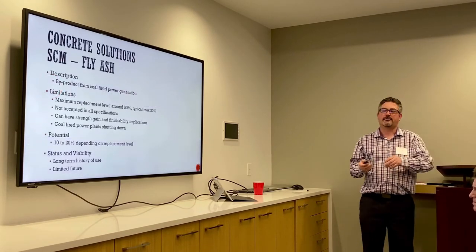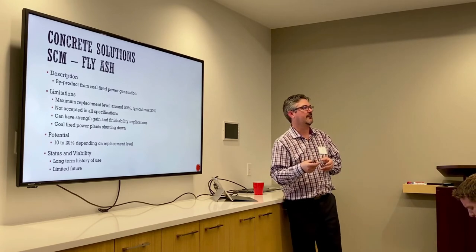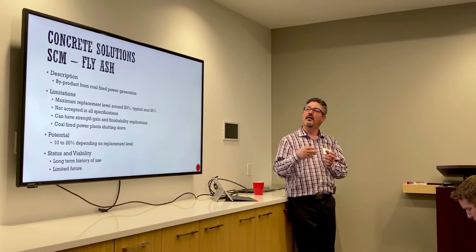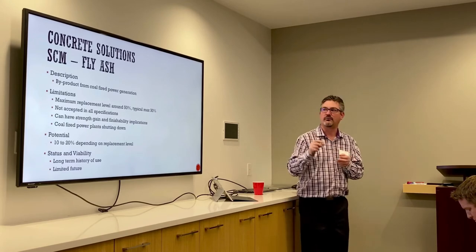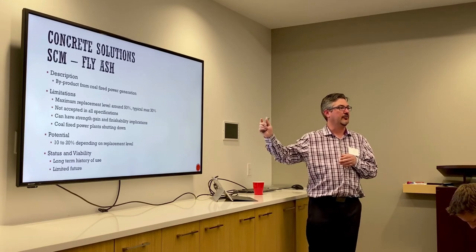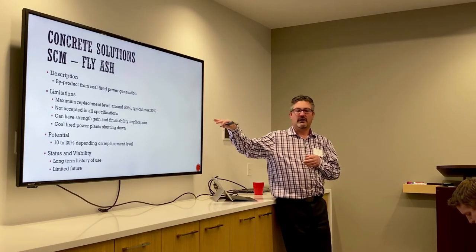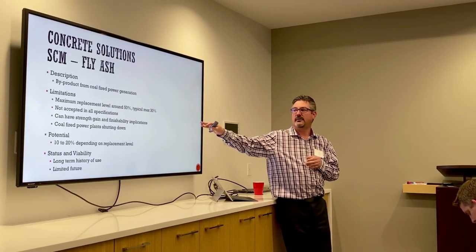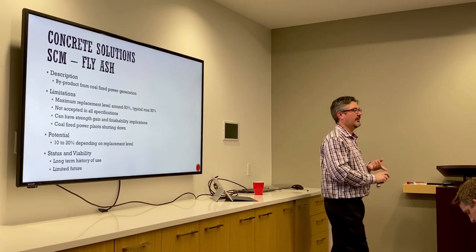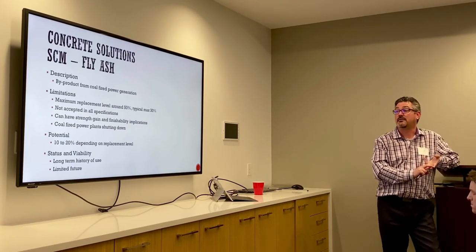So onto concrete solutions. Hopefully everyone is familiar with this one. Fly ash is what's called an SCM, a supplementary cementitious material. It's like cement, does cement-type things, but has some limitations. It's a byproduct from coal-fired power generation. Typically it would max out at about 50% replacement rate for cement, but most would max out at about 30%. It's not accepted in all specifications, and can have implications as far as project schedule, finishability, placeability, things like that. Those are things you need to be aware of if you're doing this.